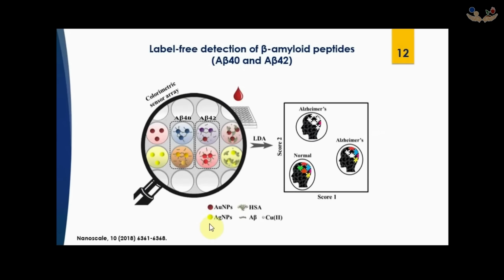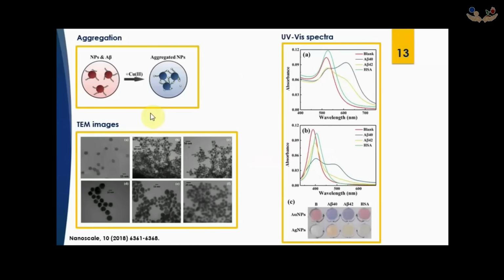For example, we used the aggregation mechanism to develop a nanoparticle-based colorimetric sensor array by utilizing label-free gold and silver nanoparticles for visual detection of beta-amyloid peptides 42 and 40, and also human serum albumin. Different aggregation behavior of nanoparticles, through the conjugation of nanoparticles with beta-amyloid peptides and then coordination of beta-amyloid peptides with copper ion, leads to diverse spectral and color changes.